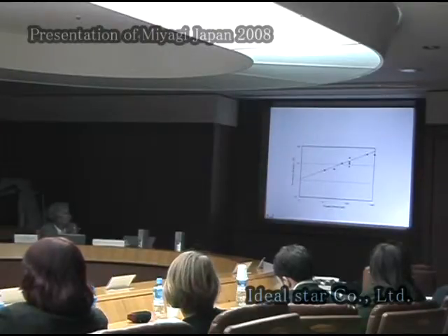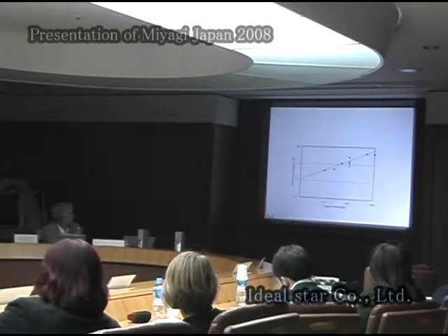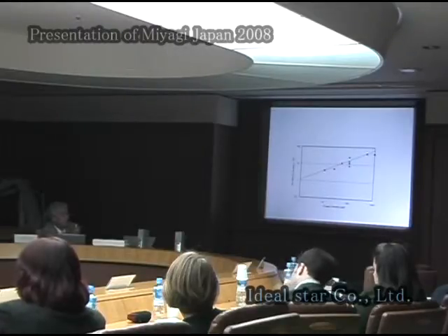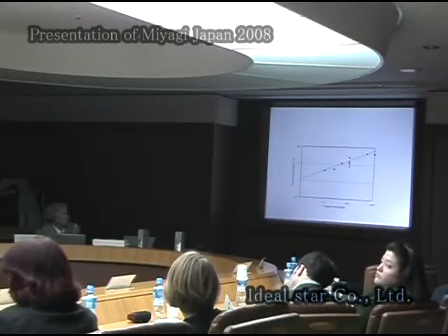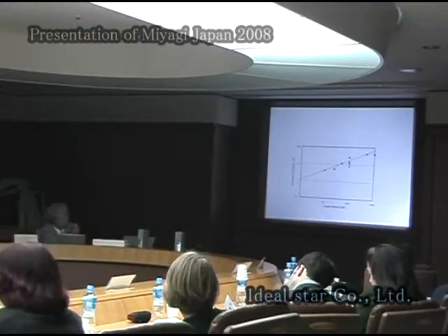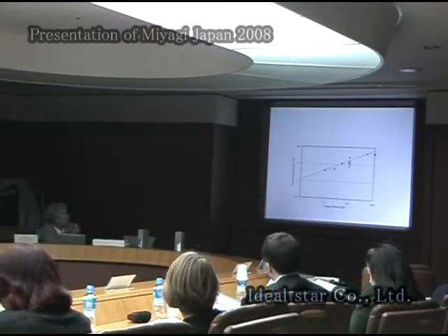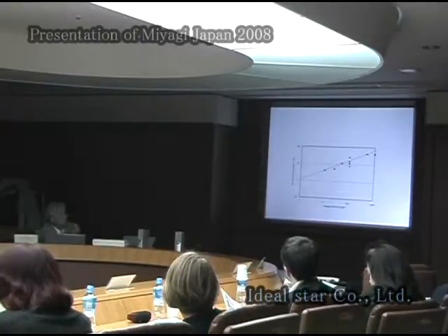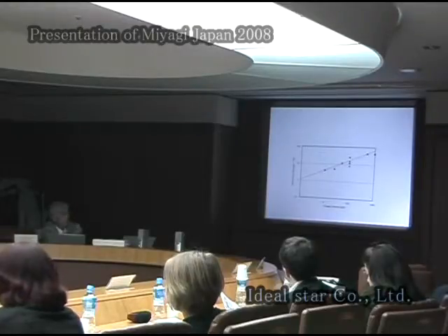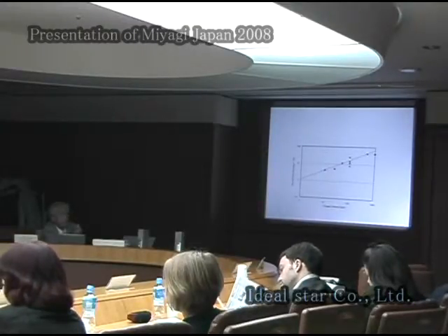This is one of the experimental results. The conductance change is plotted as a function of oxygen content in nitrogen gas. You can see that a change of nearly several percent is clearly observed at an oxygen content of 10 parts per billion. We can expect that 1 part per billion of oxygen content can be detected by using a fullerene sensor.